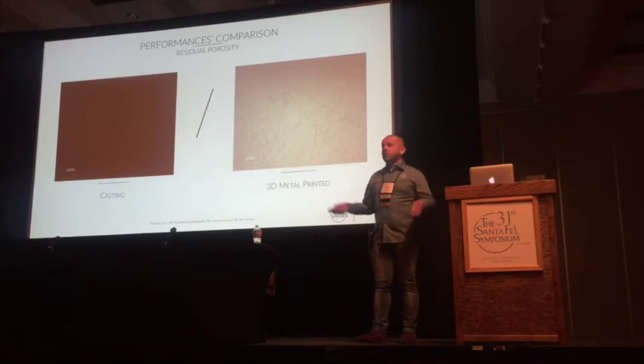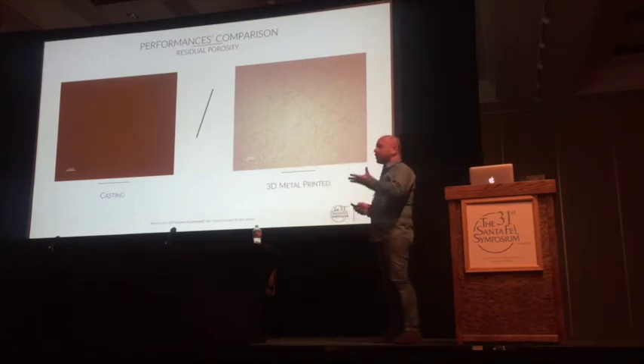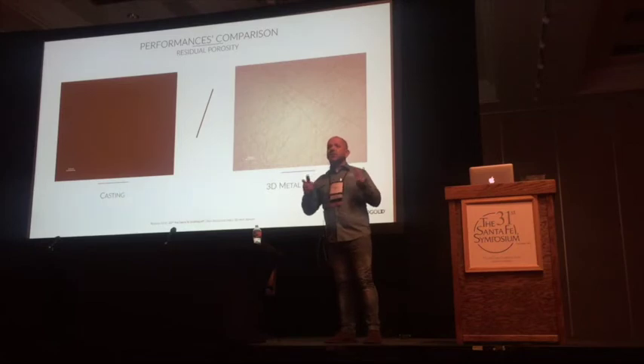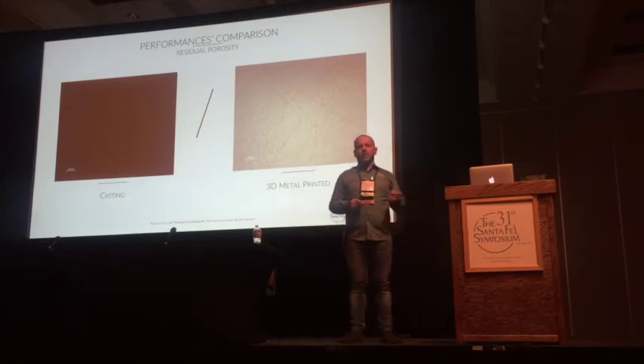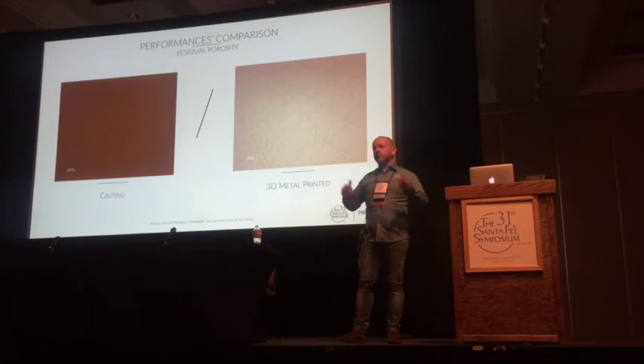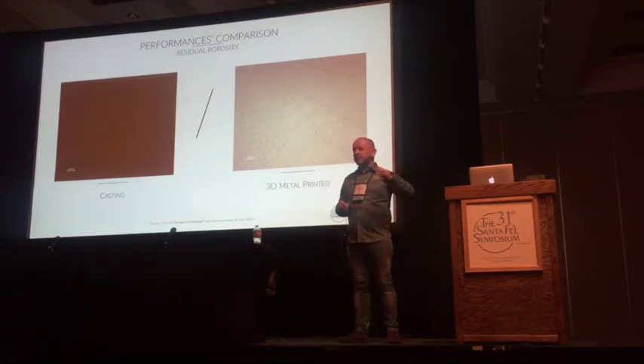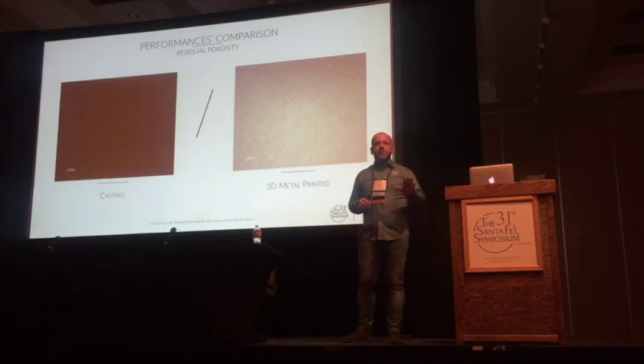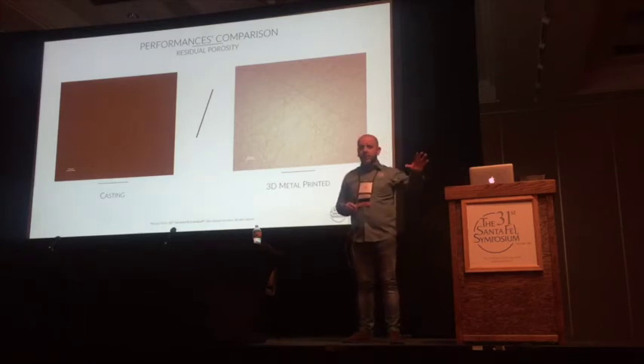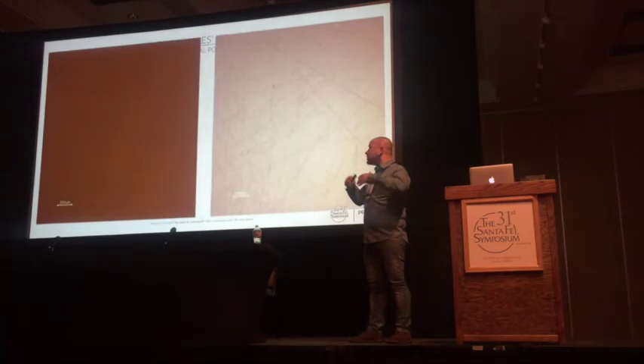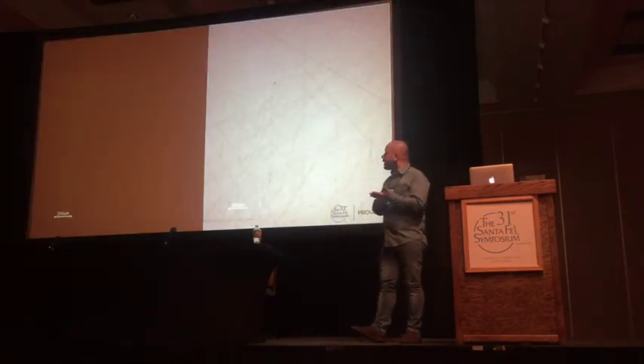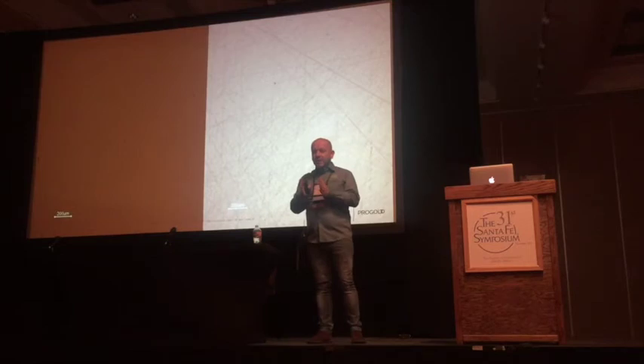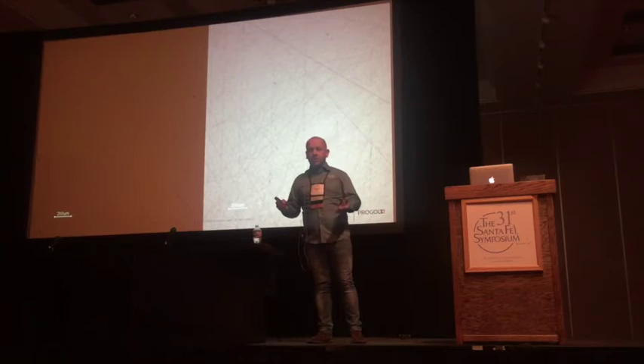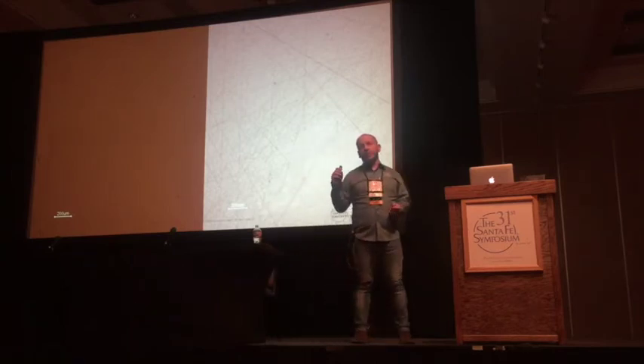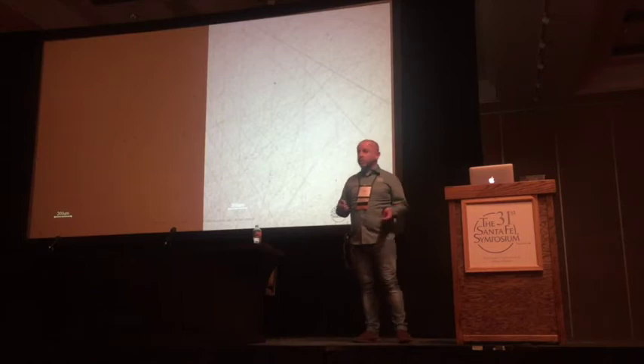About residual porosity, we spoke several times during the past years. What I can say, even this one is not a reason to 3D print the parts. We got only a few inquiries where the customer was not able to cast, which maybe depends on him. But in general, we can say that comparing a typical as-cast part and an as-printed part, after polishing of course, the as-printed one is a bit more dense than the as-cast one.